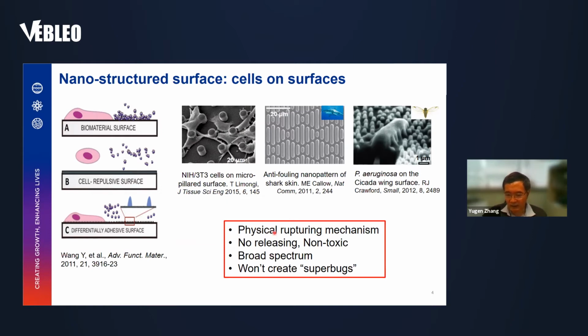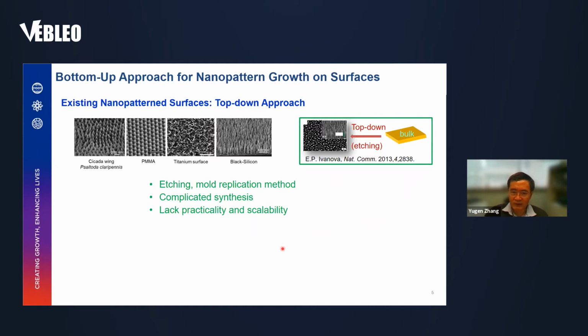So based on these properties, we are interested in developing this type of nanostructured surface to create a self-disinfecting surface. When we look at the nanopatterned surfaces reported in nature or by other people, most of them use a top-down approach. They start from bulky materials and then go by etching or mold replication methods to develop the nanostructure. Showing here are some examples. This is a natural one, and this is PMMA, titanium surface, or black silicon. These were all created by etching or mold replication. It is a top-down method, quite complex, and lacks practicality and scalability.